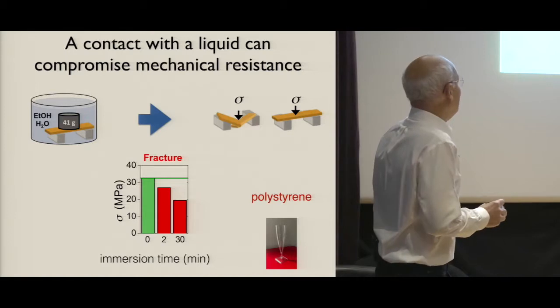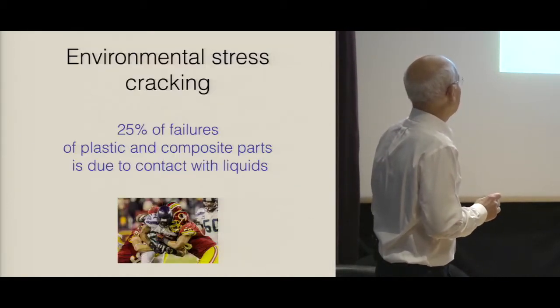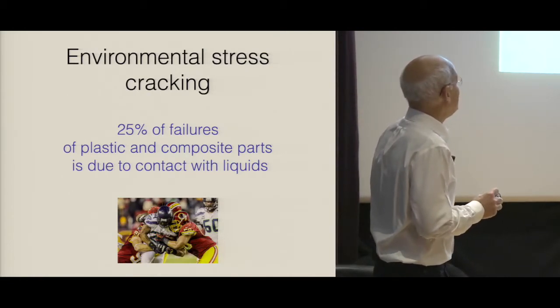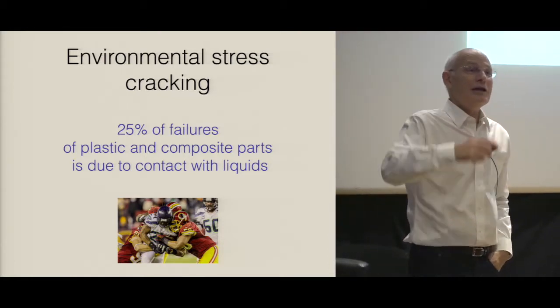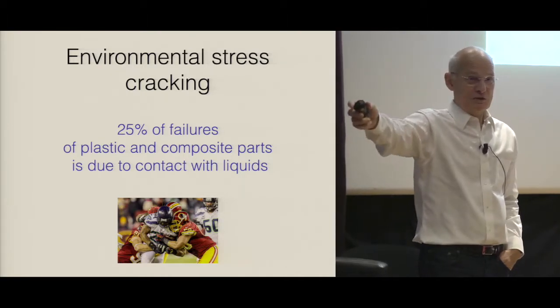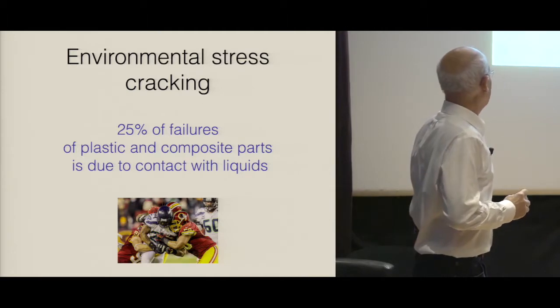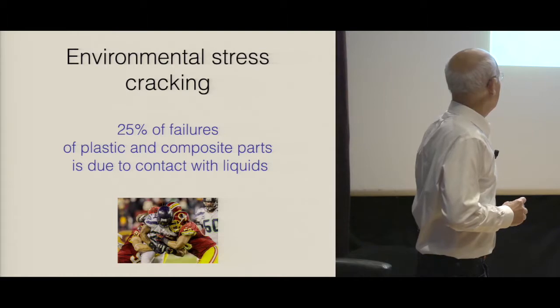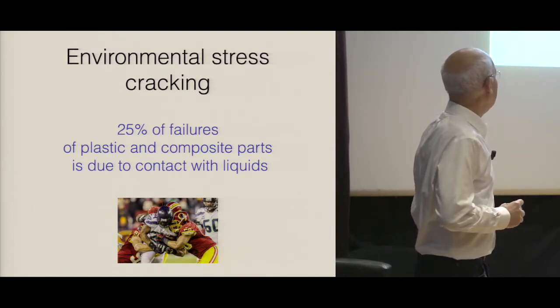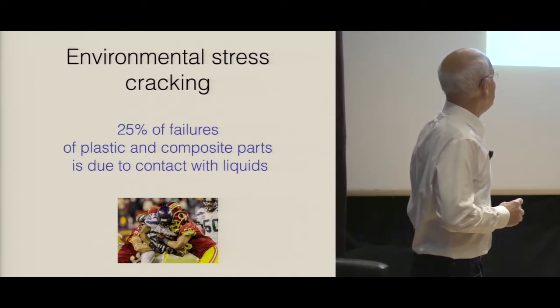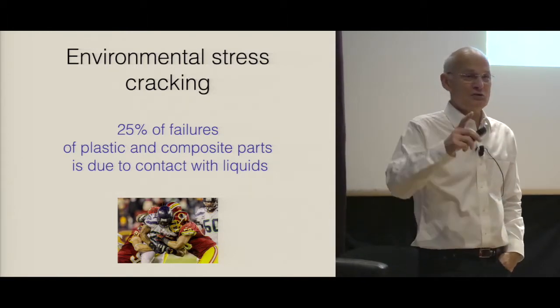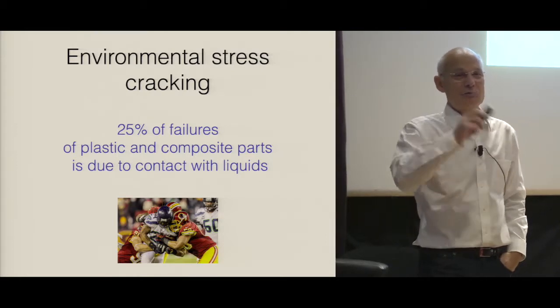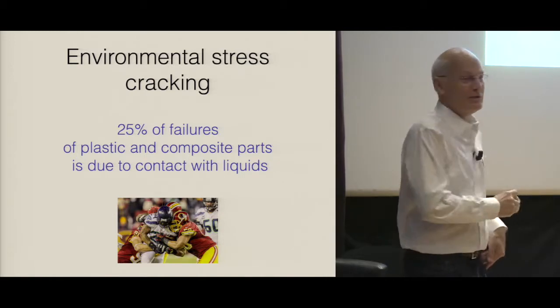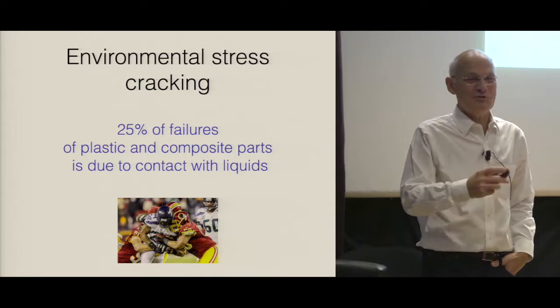So again, you may think, okay, you cannot make glassware from plastics, but actually, this phenomenon, this fragility in the presence of liquids, is called environmental stress cracking, and a quarter of failures in all applications of plastics come from this phenomenon. And this was special for my recent talk in the US, because this is a very serious problem. If you have a football game, you have impacts which are quite frequent, and they noticed that these helmets break very easily, and they break very easily because the players put a sticker, and in the sticker there was a little bit of solvent in the glue, and they were losing their brains because this helmet became very fragile. So you believe me now that it's a very important problem.